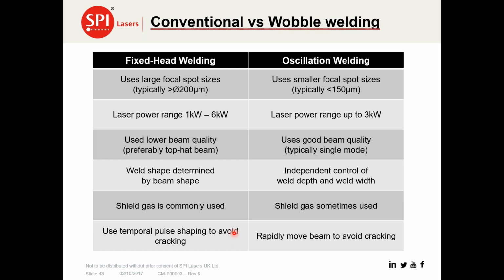Moving now on to other welding opportunities. Firstly, I'll just look at the differences between conventional and wobble welding. What I'll try and do is focus on wobble welding applications, because conventional welding applications have been around a long time, and people are well versed with the capabilities of that process. Conventional tends to be fixed head using large spots, high average power, lower beam quality lasers, preferably a top hat, which is what is generated from a re-imaged end of a fiber, and the weld shape is determined by the beam. You typically use a shielding gas, and you would use some pulsing to avoid potentially cracking.